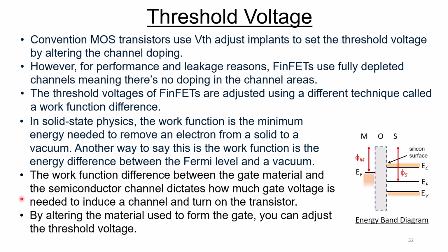Threshold voltages. Conventional MOS transistors use VTH adjust implants to set the threshold voltage by altering the channel doping. However, for performance and leakage reasons, FinFETs use fully depleted channels, meaning there's no doping in the channel area. The threshold voltages of FinFETs are adjusted using a different technique called a work function difference. In solid-state physics, the work function is the minimum energy needed to remove an electron from a solid up to a vacuum. Another way to say this is the work function is the energy difference between the Fermi level and a vacuum. The work function difference between the gate material and the semiconductor channel dictates how much gate voltage is needed to induce a channel and turn on the transistor.